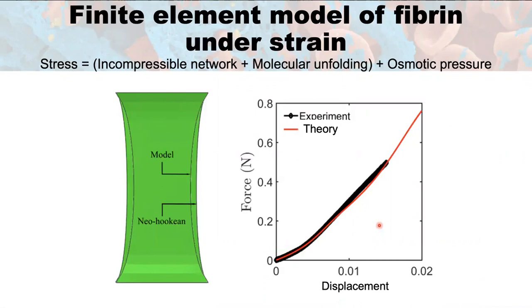So we now have a macro scale experimental approach. We have a micro scale experimental approach looking at the microstructure. And then lastly, we're using a modeling approach, a finite element model, to look at the fiber network under strain, which was done in collaboration with Prashant Purohit at the University of Pennsylvania. And so he worked to develop a model of the fibrin network that looks at the strain stiffening properties of the incompressible fibrin network, coupled with the molecular unfolding that occurs within the fibrin network as the sample is strained, and then the interaction between the solid and the liquid phase seen through the osmotic pressure, the expulsion of the serum from the clot or the plasma from the clot while the fibrin is being stretched.